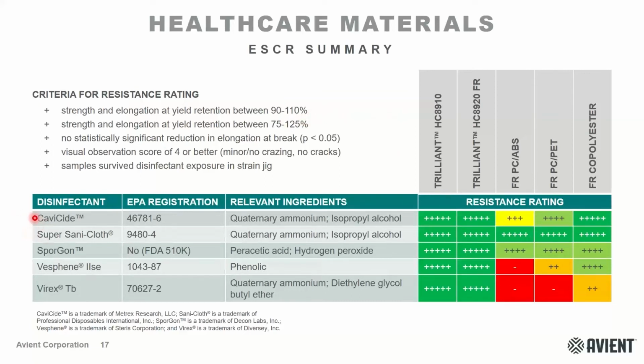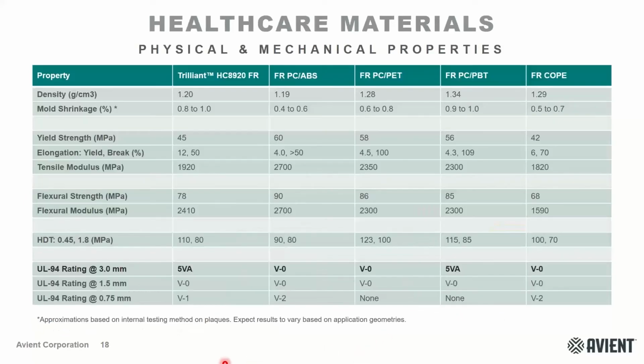And as I said, we tested against a number of different disinfectants that are listed here. And so all of these are pretty common healthcare disinfectants for our Trilliant materials that we tested against. And again, you can see FR PC/ABS, FR PC/PET failing in the jig against Virex TB, which is one of the more difficult ones, also poses some problems to the FR copolyester as well. And so overall, the Trilliant materials here perform very, very well against this swath of disinfectants.